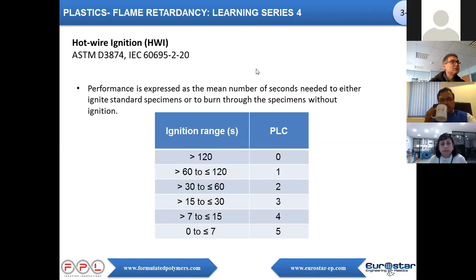Then too, you are measuring the time. So you see, for example, a material which takes fire in less than 5 seconds has a very high PLC, which is not a material suitable for the application. But we have material that can withstand above 2 minutes, meaning that it will have a PLC 0. In our range, we have many materials in the range of PLC 0, 1, and 2. And in some cases, it's really of vital importance, because if you have a material of PLC 1 or 0, you will see maybe in the next presentation, you can choose material that has still V2 or even HB performance.